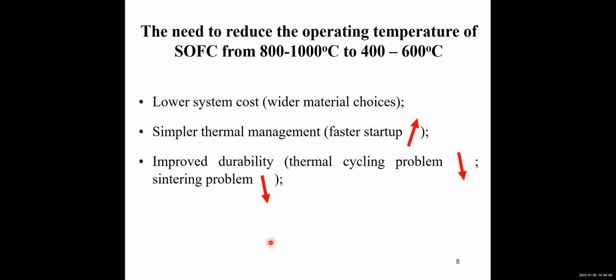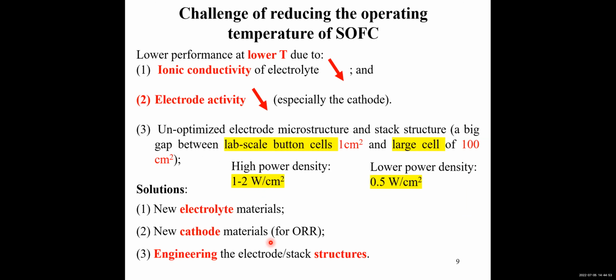However, when we reduce the operating temperature down to about 400 to 600 degrees Celsius, the actual performance of SOFC will also decrease, mainly due to the decreased ionic conductivity of the electrolyte, as well as the decreased electrode activity. So these two will increase the ohmic loss, as well as the electrode polarization resistance.